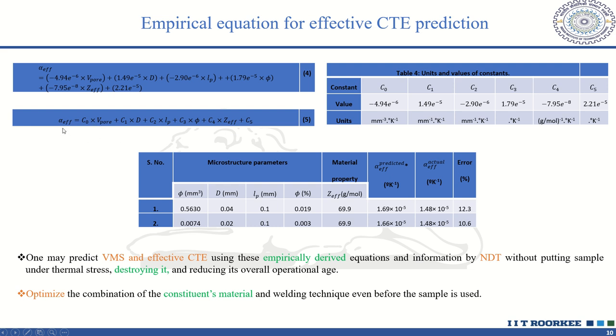The parameters which affect it are volume of the pore or shape of the pore, size, location, total porosity content in the braze or joint interface region, or the effective molecular mass of the joint assembly. The values of different coefficients are listed in this Table 4, along with the units. And then the CTE parameter for some random combinations is predicted, and it is found that the difference between the actual and predicted effective CTE value is between 10 to 12%.